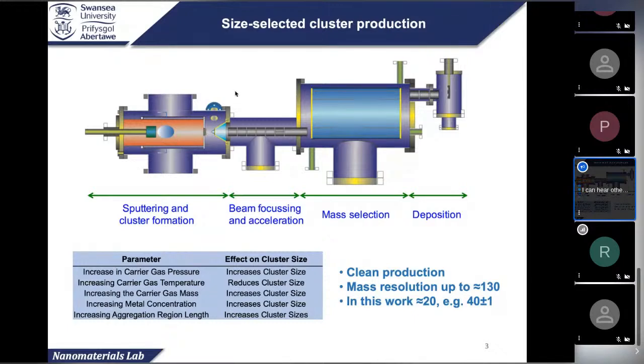Then those clusters go to the second chamber, which is the ion optics. In this chamber, we extract the center part of the cluster beam and focus it into the mass filter, which is the third section called mass selection. In this one, we use a lateral time-of-flight mass filter. Basically, you have 4 plates, numbered 1, 2, 3, 4 from the bottom, with a section open in the middle, for plates 2 and 3.